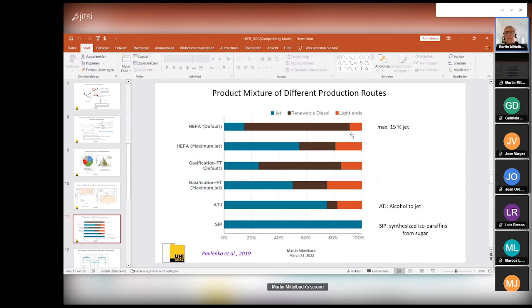Then you get a lot of so-called renewable diesel, which could be used on the street for heavy duty and light duty vehicles, and light ends. So maximum 15%. You can maximize this or modify the whole process up to 50%. So the optimum procedure for this HEFA production or HVO production can give you about 50% of jet fuel.